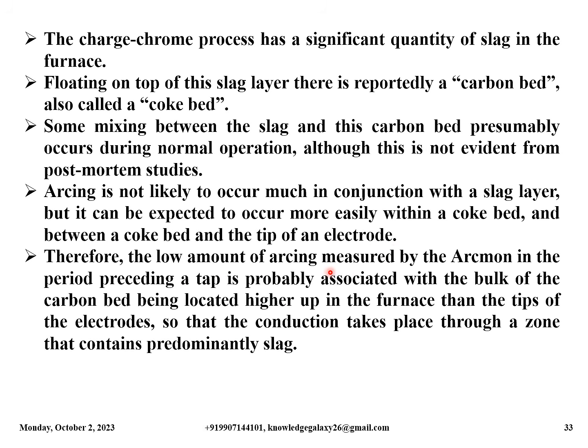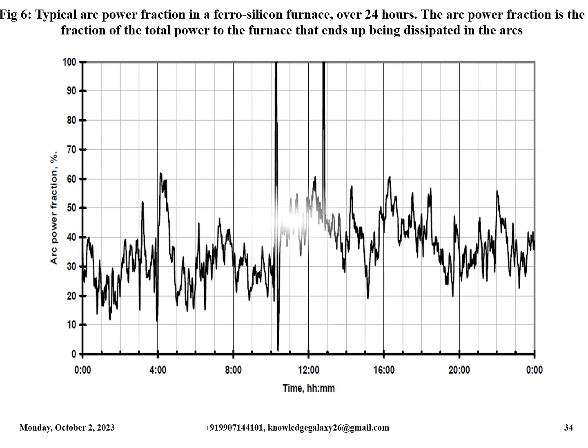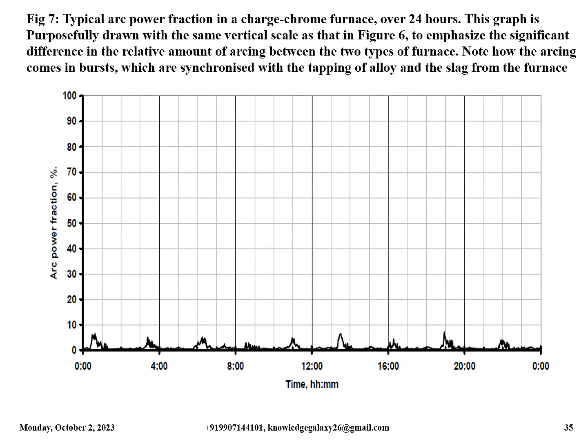Therefore, the low amount of arcing measured by the arcmon in the period preceding a tap is probably associated with the bulk of the carbon bed being located higher up in the furnace than the tips of the electrodes, so that the conduction takes place through a zone that contains predominantly slag. So this is figure 6, which I have just explained earlier. You can pause the video and observe the things. And this is figure 7, which I have also described.